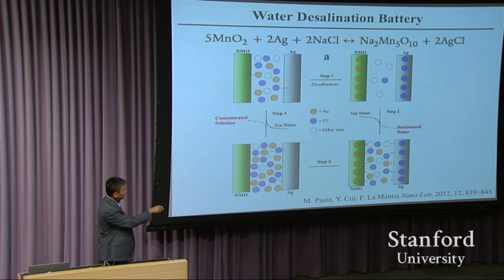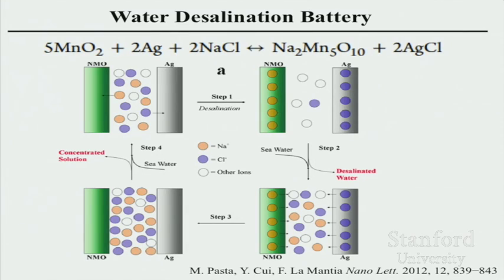You flush in the seawater. Now, once the seawater goes in, you do the next step. That's you charge up these batteries. When you charge up the battery, you dump these ions, sodium and chlorine, back into the seawater. So this concentration becomes higher. So fresh water comes out from here, and more concentrated, salty water flows out. Now you put in seawater again and repeat the cycle. So every time you come to here, you have fresh water. And you are doing a discharge of the battery and a charge of the battery, and then you recover back. This is the whole thing. Now you can do charge, discharge many, many times. You just repeat using these batteries for water desalination.